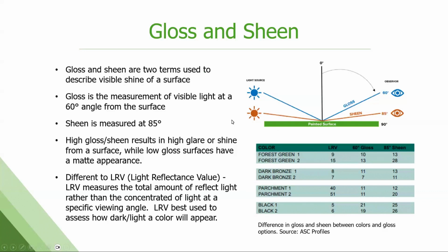Let's talk about gloss and sheen, and this gets a little confusing with reflectance sometimes. Gloss and sheen is how we describe the visible shine off of the surface. We measure it at either a 60-degree viewing angle, or 85. 60 degree is gloss, 85 is sheen. High gloss, high sheen is a very high glare or shiny surface. Whereas if you go to low gloss, low sheen, you're going to have a very matte appearance. And we are seeing a trend to this, especially in residential, right? No one wants a very shiny, glary roof in your neighborhood or next door to you. So we're seeing movement to low gloss, low sheen, or a fully matte finish that doesn't have any kind of reflection on it. This is different than light reflectance value, which is the amount of light, kind of how light or dark it is.